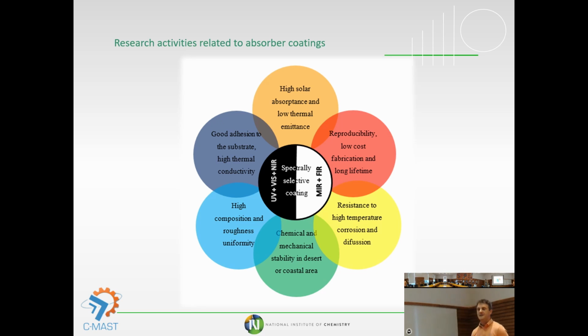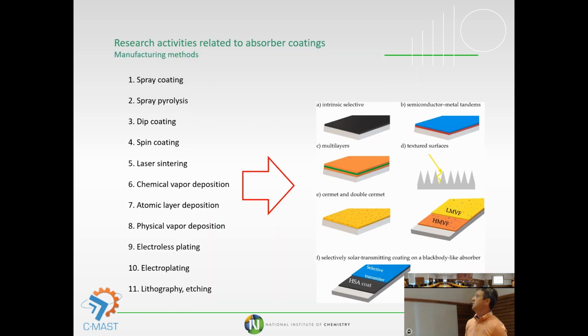Also, it should be stable in the desert region, maybe with some salt in air, so corrosion stability. We work quite a lot with abrasion resistance, just because you could expect heavy sandstorms in the desert, and of course composition, roughness, uniformity is important, and so on.